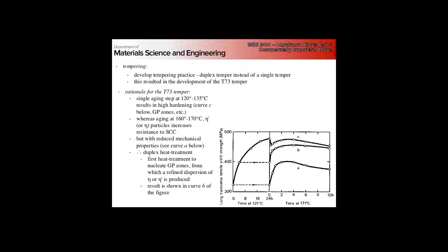We get a hardening curve that looks like this, after this is up to 24 hours. So fairly high strengths, around 480, but bad stress corrosion. If we aged at a higher temperature, 160 to 170, we get a hardening curve that looks like this - not nearly as strong, but a much better resistance to stress corrosion cracking. This is a fine dispersion of eta prime or eta particles.